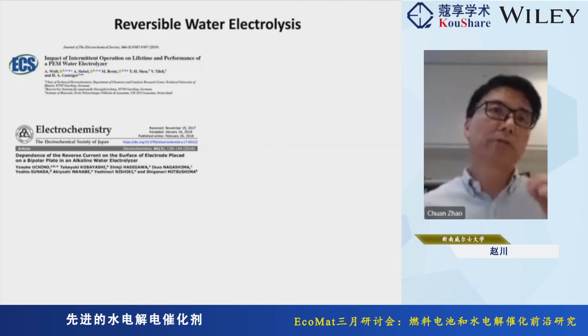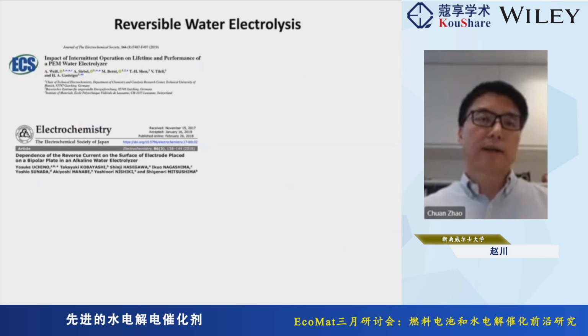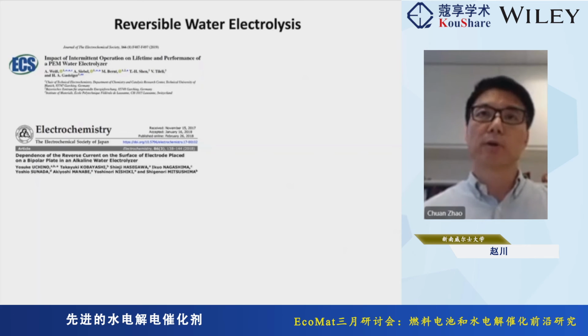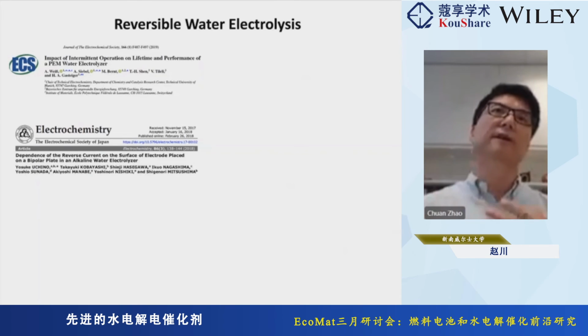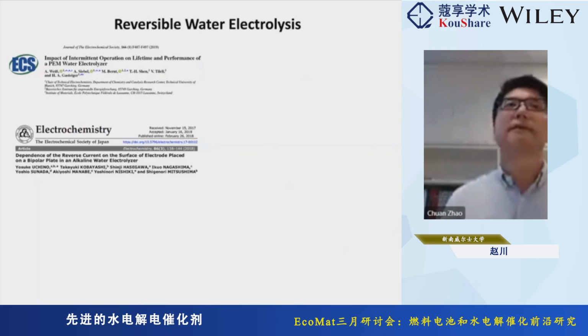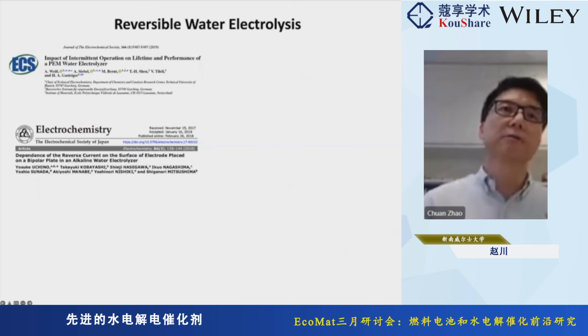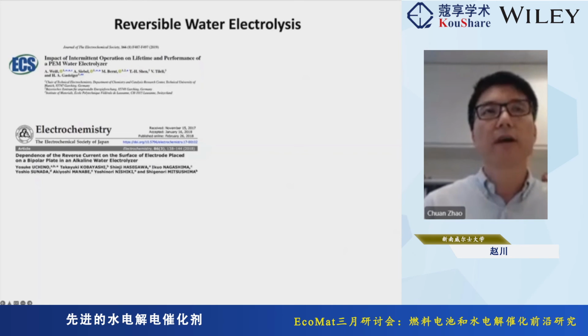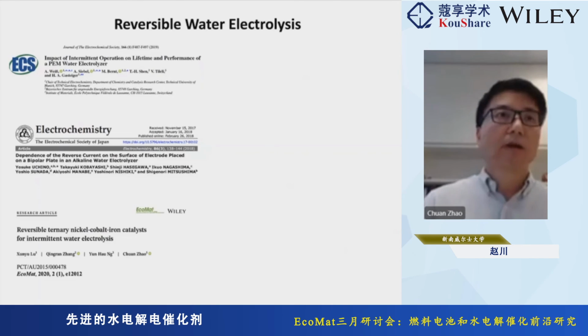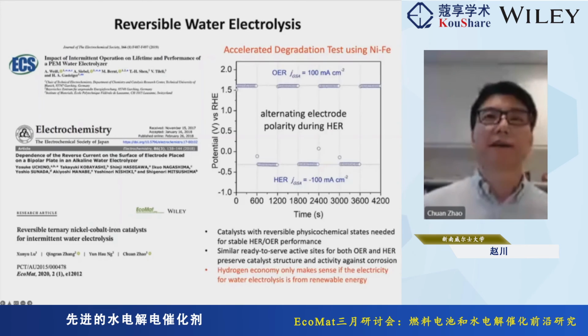One of the problems in the water electrolyzer is stability. Most of our tested catalysts are tested under stable conditions. But in reality, a water electrolyzer often has to be shut down and started up. At that process, a reverse current develops, which causes significant corrosion reactions. We first introduced a reversible water electrolysis catalyst 7 years ago. We reported a nickel, cobalt, iron catalyst. We filed to patent it, but we published it about 2 years ago in EcoMat. That's our first EcoMat paper.